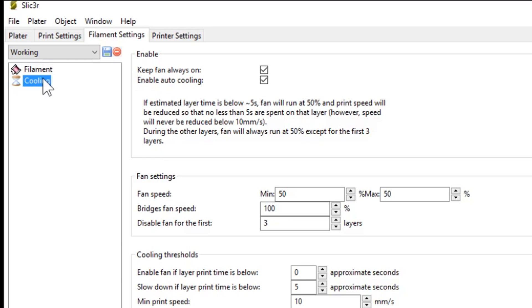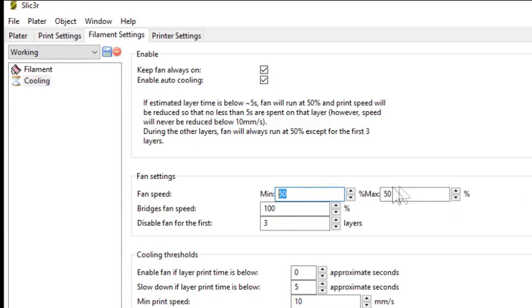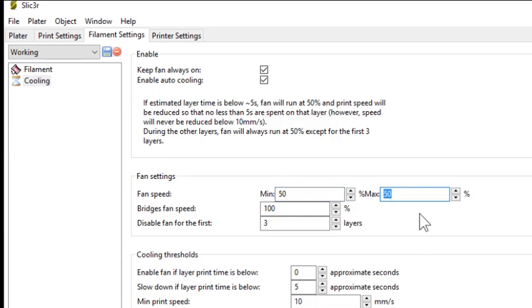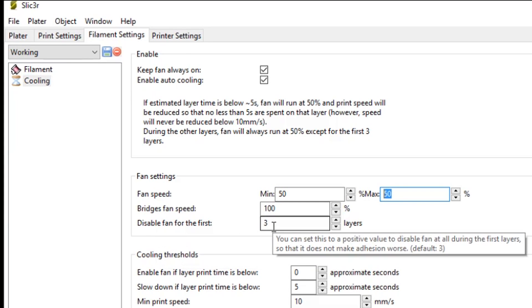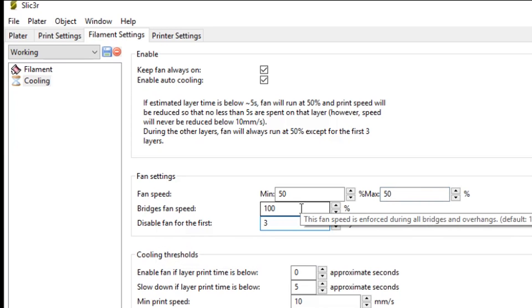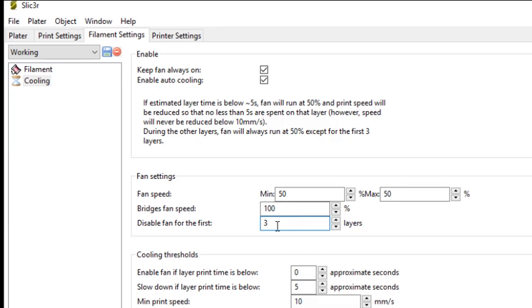Cooling. So this is the part cooling. This is also quite important. I have the fan set full time to 50% with printing with PETG. I find I need to print with the fan. Otherwise, I start to lose detail in the part, especially when there's overhangs. But I disable the fan for the first three layers. This is to ensure that the part sticks down firmly to the blue painter's tape before the fan kicks in.